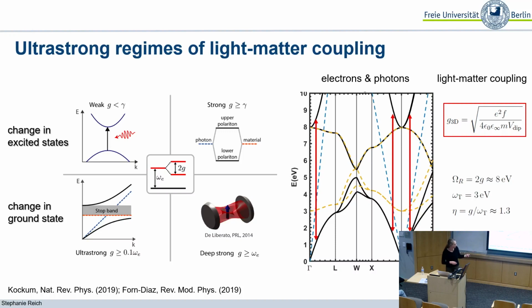We were also able to develop an analytic model that describes this situation, the 3D crystal, in a similar way of thinking as we did for the single excitation in the cavity. The expression for the light-matter interaction is actually the same as in the cavity, except that the mode volume of the photon gets replaced by the volume that this dipole occupies. That's something like the unit cell of the crystal that we consider. And because you can confine electrons and also phonons much better than you can confine photons, the interaction that you get in crystals is actually much larger than what you had for the cavity. Okay, so much for the theory.